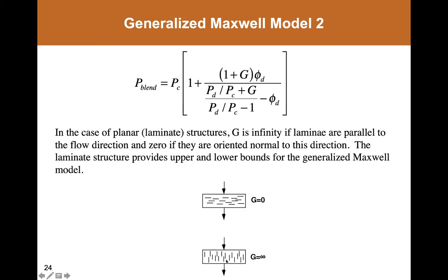And you could imagine that if these platelets or laminates are impermeable or much less permeable than the continuous matrix, then whether they would be oriented parallel or perpendicular to the direction of transport could have a significant bearing on what the permeability of that blend was, even at the same volume fraction of this dispersed phase. One could have very different permeabilities depending on the platelet or laminate orientation.